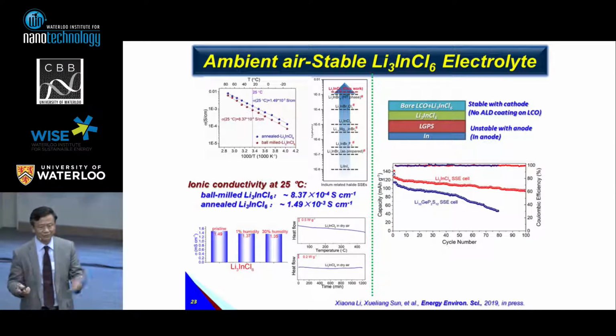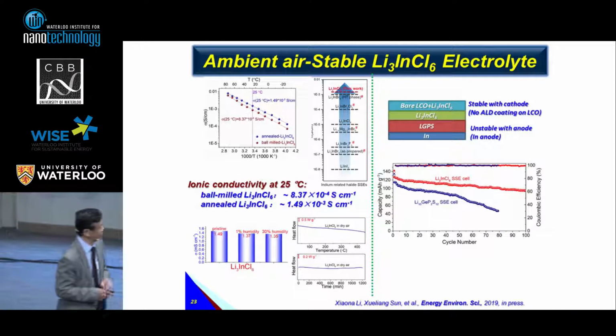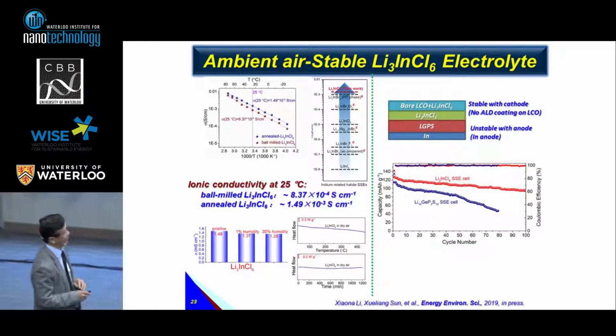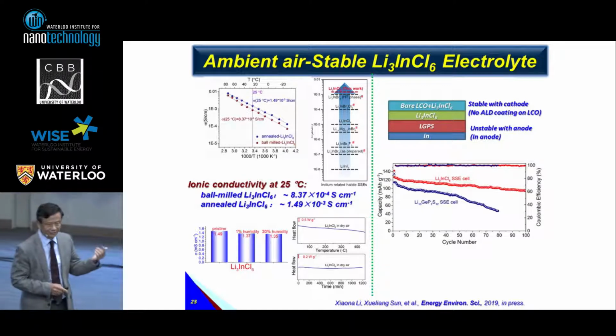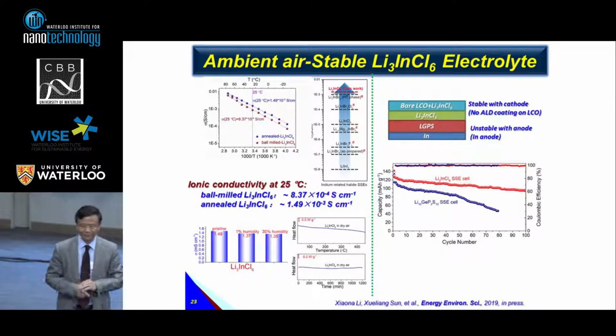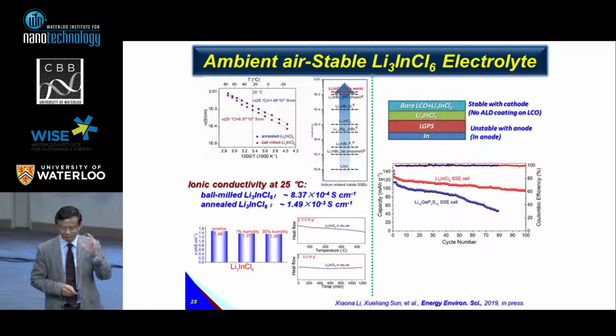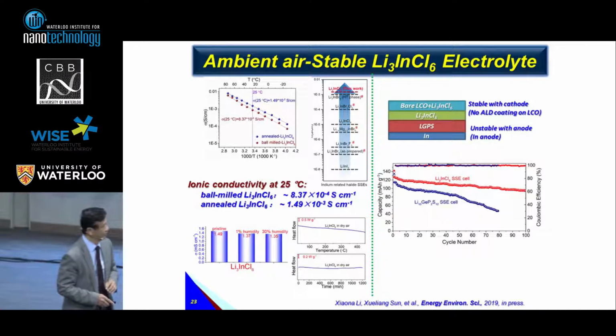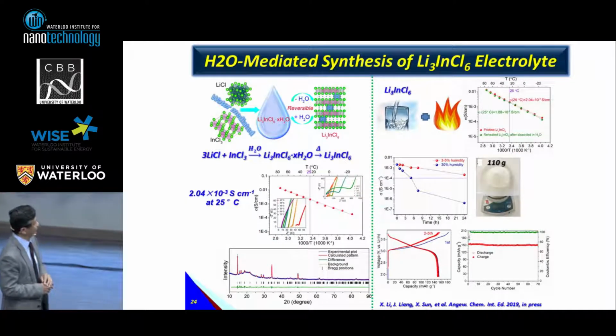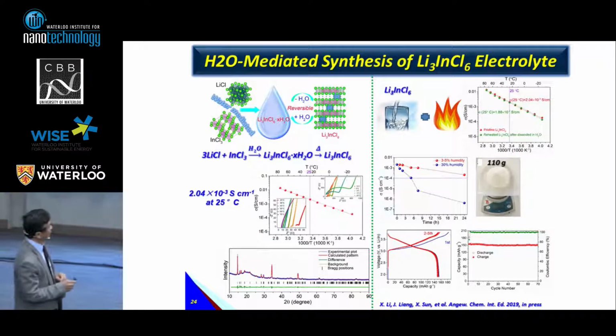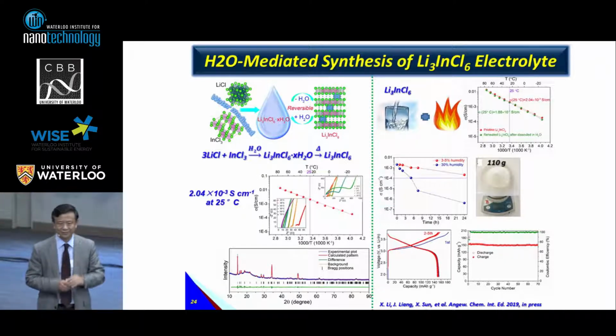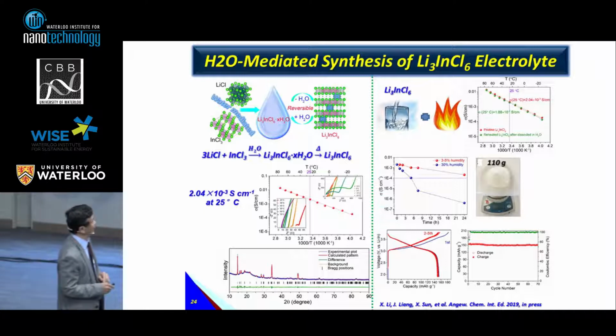Because sulfide you cannot handle in the air, it has a reaction. But this one you can handle in the air. So compared with the sulfide, this kind of electrolyte is very stable. In this method we're using ball milling, but we try to scale up for industry application. So actually last week we just reported, using a liquid-based method, we can make this kind of electrolyte. So also very high ionic conductivity.